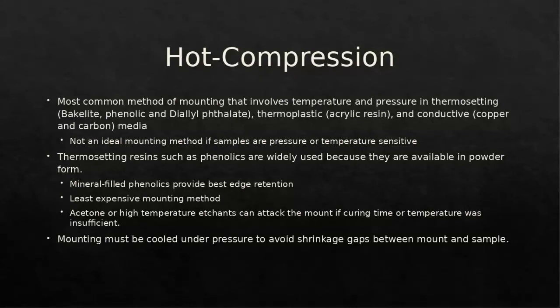With hot compression mounting, the sample must be cooled under pressure, and that's just to help avoid any shrinkage gaps between the mounting media itself and the sample. If you happen to pull the sample out too early and let it air cool, then since it didn't cool under pressure, shrinkage will move away from your sample, opening up gaps, and once again, gaps collect debris and increase the amount of bleed out you have when working with etchants and or alcohols and stuff like that.